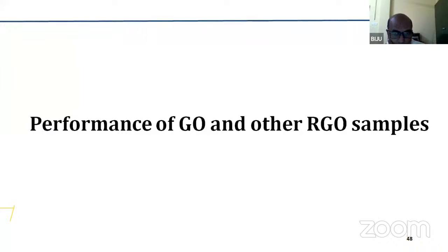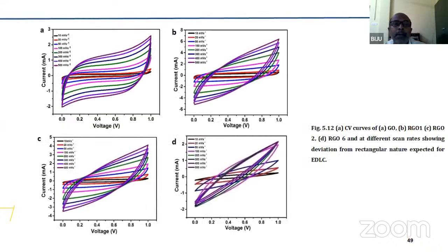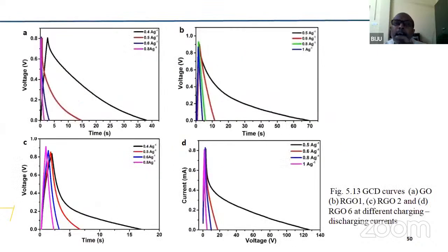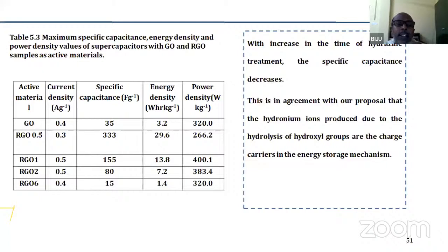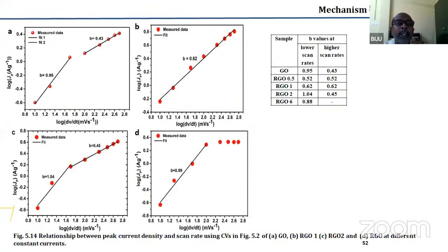So we did this with the other samples also, where the OH concentration was less compared to this particular sample, and we found that when there was considerable OH concentration, we could store energy, but the performance was best for the sample which we discussed first, and the behavior was similar in all the cases. The only thing was the specific capacitance was maximum for the 0.5 sample, which contained the largest quantity of OH ions attached to the graphene layers.